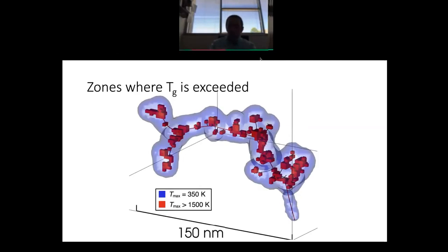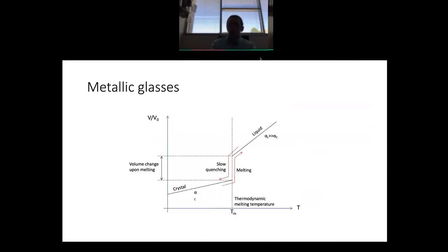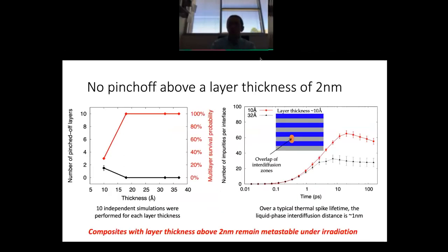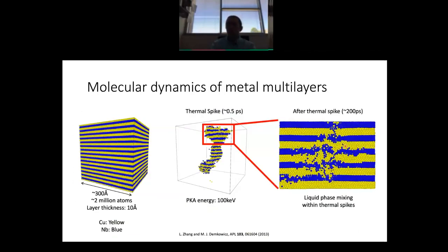So in the example that I gave here, the simulations that I showed you, the thickness of the layers is small enough that the interdiffusion zones from neighboring interfaces are overlapping, right? So you get substantial interaction between neighboring layers of copper, neighboring layers of niobium. If the layer thickness is larger, then that overlap doesn't occur, and you just get a little bit of roughening of the interfaces and nothing else, and that recovers to the flat interface after some thermal annealing. And in the phase field model, that's not really sensitive to the thickness of the interface, so long as you're only changing it by on the order of a factor of 2.